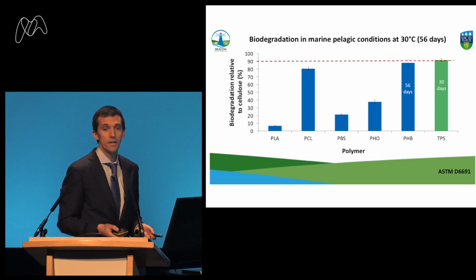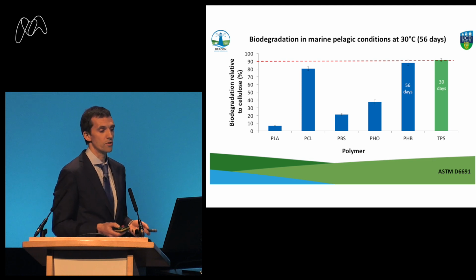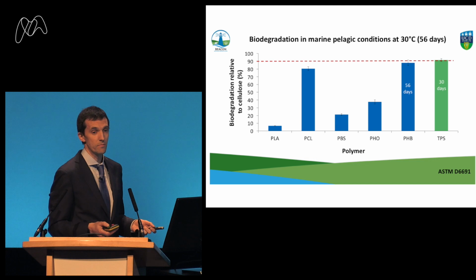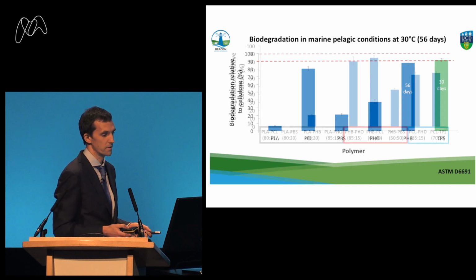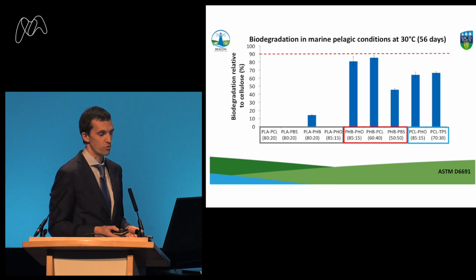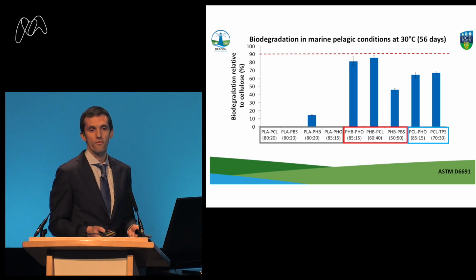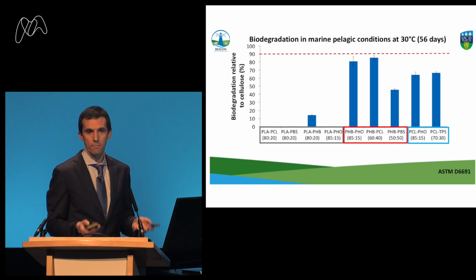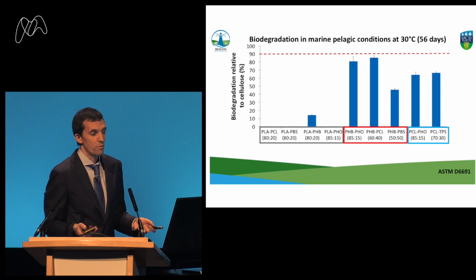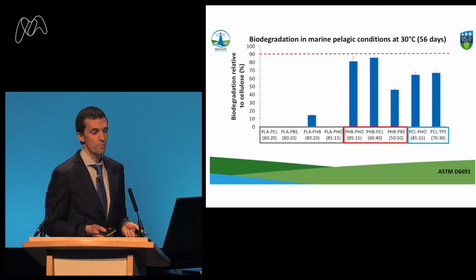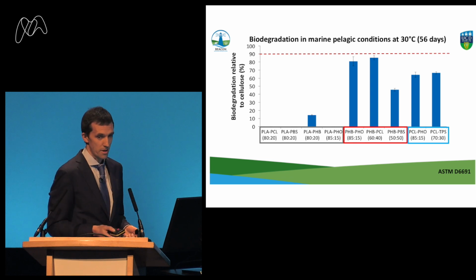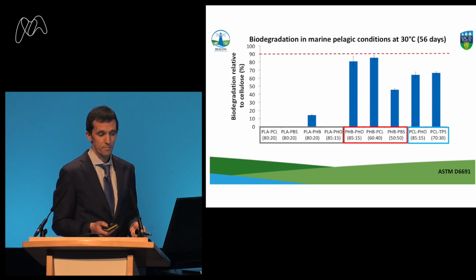So again, these plastics, when they get into the marine, are not going to degrade or meet the standard. Some of them are degrading reasonably quickly, but they're not making the standard, except for TPS. And then if we look at all the blends, and I'm not going to go through all of them, PLA performed very poorly in the marine. PHB a lot better. It got quite close to making the standard, so you are getting a lot of degradation. We would predict that it's going to take around 70, 80 days for PHB-based polymers to degrade in the ocean, which is still a relatively short time. But PLA, you're talking years, hundreds of years, the way it's looking. And PCL and PCL-TPS are pretty good, but they still don't make the standard.